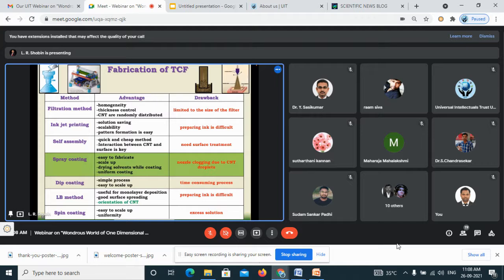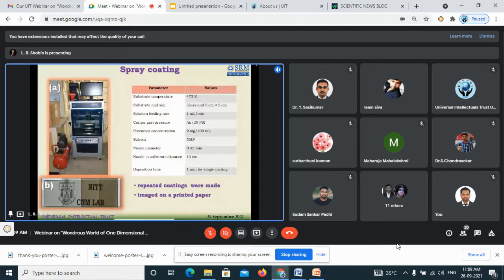And drying of solvents using this spray coating: once you spray, meantime you can dry it also. So you can easily achieve a uniform coating and you can scale up the process to any arbitrary substrates also. So that is very interesting. So I'm sticking with the spray coating process. I have used this spray coating machine for my fabrication of these transparent conducting films.